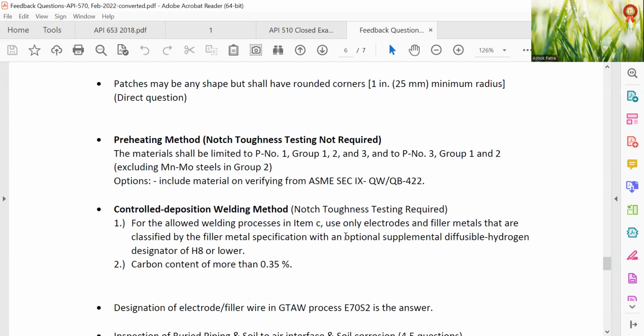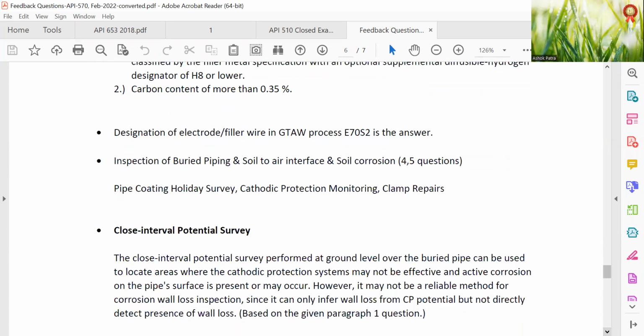Controlled deposition welding method, notch toughness testing required for the allowed welding process in item C. Use only electrodes and filler metals that are classified by filler metal specification, optional supplemental diffusible hydrogen designator H8 and lower. Carbon content more than 0.35%. Designation of electrode filler wire, GTAW process, ER70S-2.